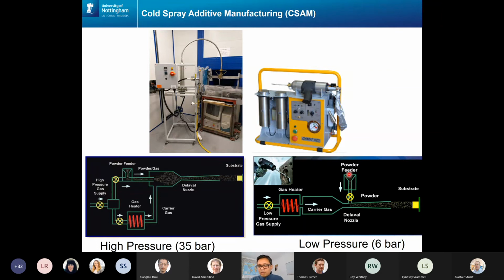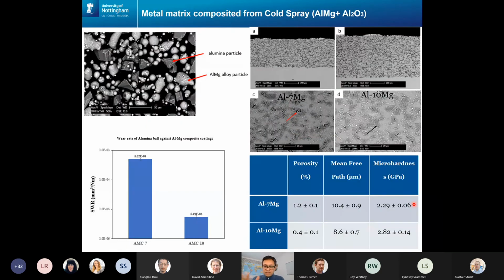Similarly, in a low pressure cold spray, we also add a ceramic component. And when these particles exit the nozzle, it then starts producing that metal ceramic mixture. You can start making several millimeters thick deposits using this cold spray additive manufacturing. This is an example. This is unpublished work. Here we were developing MMCs with aluminum magnesium with alumina powder. So here my reinforcement material is alumina and the powder is a gas atomized aluminum magnesium alloy.